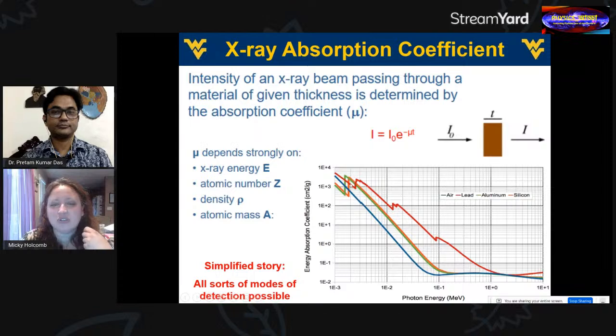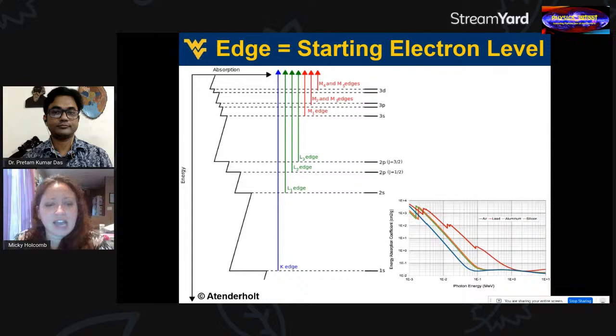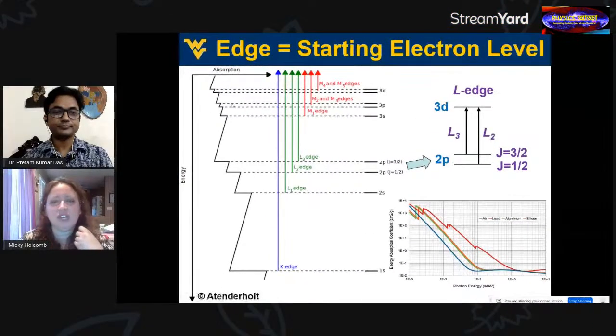And you can see that for different elements, you see this general downward trend, but you get some edges. And these absorption edges can tell you a lot about the material. These edges have specific names. So they're actually named by, if you excite at a certain energy, you can kick out certain core levels within your system. So for example, if you kick something out of the n=2 shell, this is called the L edge.